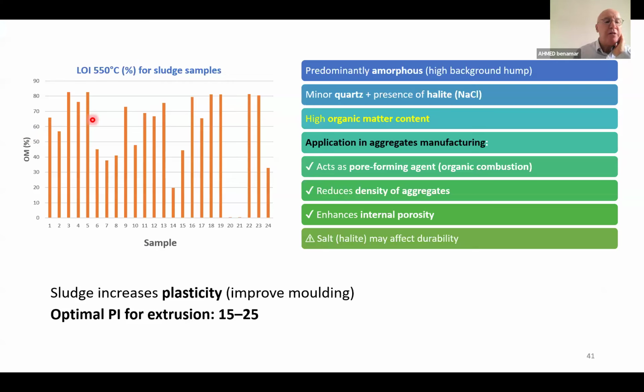This diagram shows the distribution of the organic matter content in different samples of sludge. So we see that the values are very interesting, more than 40. This kind of matter is predominantly amorphous, not so much quartz, with presence of halite and high organic matter content. So it can be used for aggregate manufacturing. It can act as a pore-forming agent, or by organic combustion it reduces the density of aggregates and enhances internal porosity, but the contained salt can also affect the durability of such material.